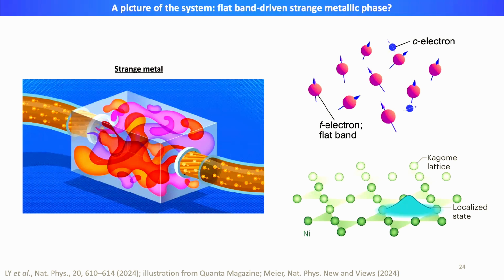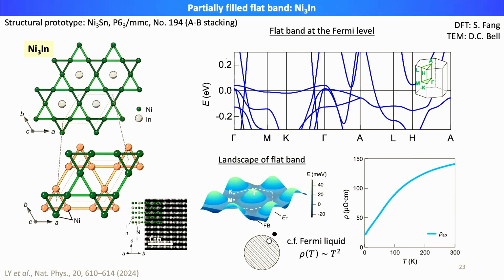So these localized states would behave as local moments as their kinetic energy is quenched. And there will be a competition between the localized moments themselves, as well as the localized moments with the conduction electrons through the Kondo interaction, and perhaps this is the driving force of the strange metallic behavior we're seeing in our flat band system. So this is indeed a quite unexpected discovery we've made, by being able to bring the flat band features to the Fermi level.